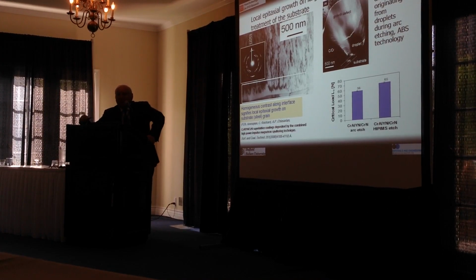This type of crystallographically perfect interfaces produced by implantation trigger afterwards during the coating growth stage local epitaxial growth. The difference which we saw, because we were practicing metal ion etching with arc for many years, but the difference which we saw with HiPIMS was that we can have local epitaxial growth on very, very large areas of the substrate.